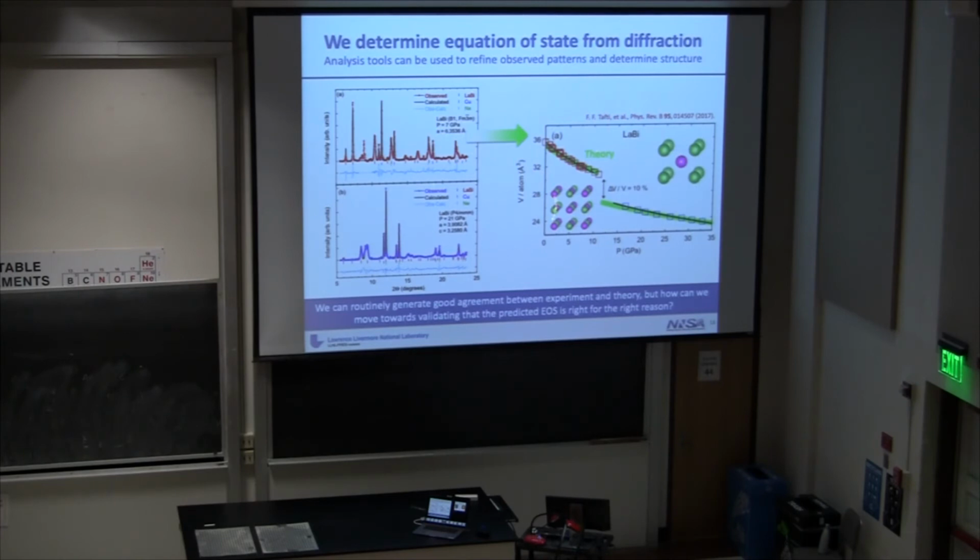It starts as a rock salt structure, so that's FCC, so it looks just like sodium chloride, table salt, and it goes into a body-centered phase. It's not BCC because it has 2 atoms, so this is basically the cesium chloride structure. So these are basically 2 classic salt structures that happened here. And so this is a common thing to see in high pressure physics.